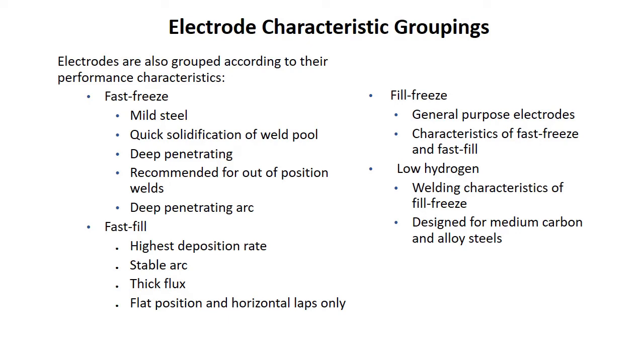Fast fill would be like a 7024 where you just absolutely need to dump some metal into a weld pool. Really high deposition rates, stable arcs, a really thick flux, and they're flat and horizontal positions only because the weld puddle is just so liquid. It takes a while to cool, and you can't weld out of position with this stuff. It just doesn't work. Then you've got fill freeze, which is our general purpose electrodes. They have the characteristics of a fast freeze and a fast fill. So it's a little bit of both.